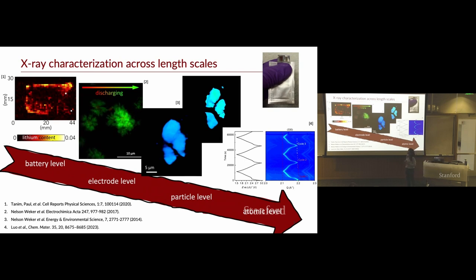This is a fast-charged battery, and I'll talk about fast charging in a more specific example. One of the issues with fast charging a battery, why don't we always go and plug Teslas into their fast chargers, is because you run the risk of plating lithium metal on your anode rather than the lithium ions going into your anode and intercalating into the graphite. And so here, without taking apart the battery, we're able to see where the lithium metal is plated onto your battery.